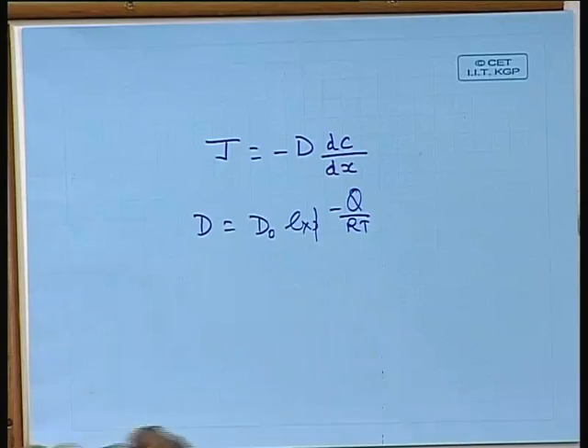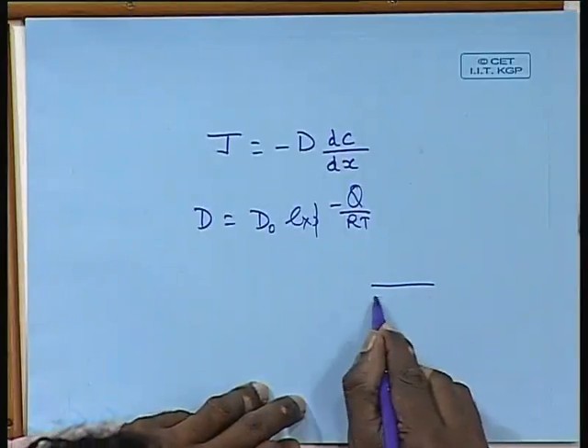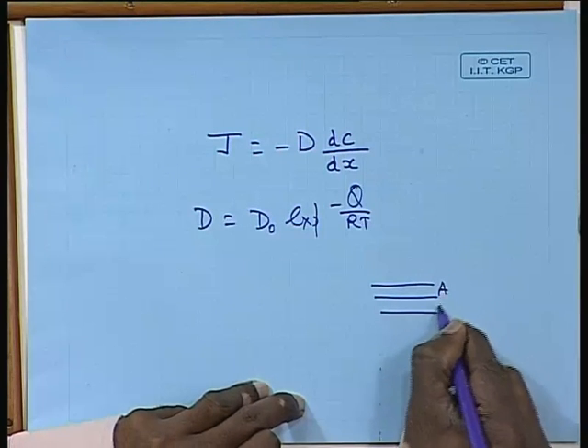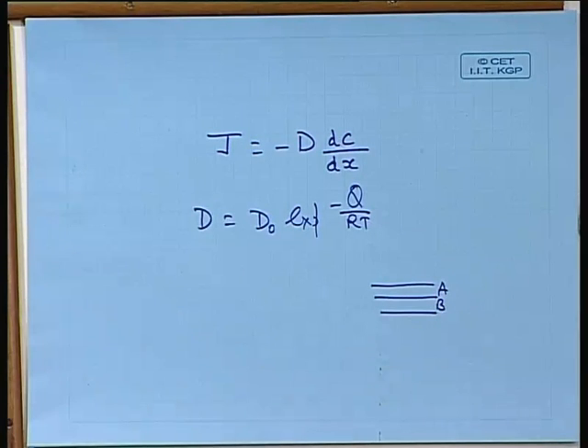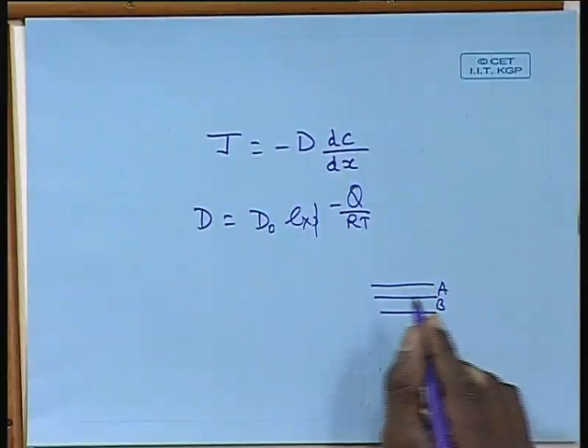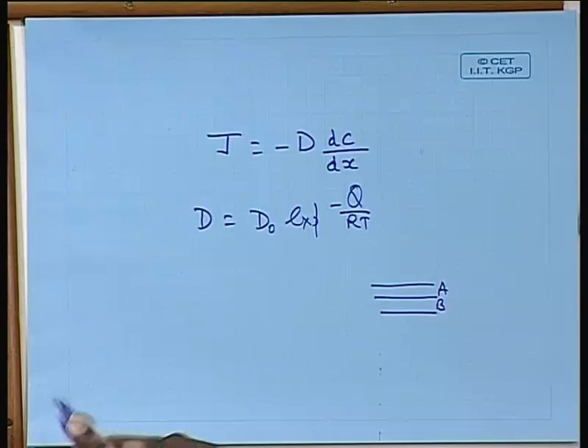When you are decreasing the size, let us assume that in ball milling you are forming alternate layers like this, A and B. If you are doing continuous milling, the thickness of the A and B keeps on decreasing, because there is continuous breaking and rewelding taking place. Because of which there is a continuous decrease in the thickness of individual layers, and if there is a continuous thickness decrease, then you can see that dC by dx increases tremendously, because the dx is decreasing. As you can see, the dx is nothing but the diffusion distance, the distance over which diffusion has to occur.